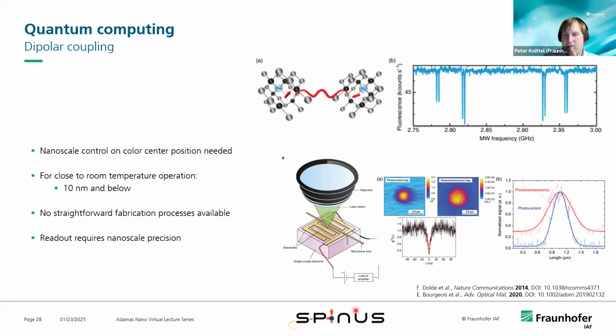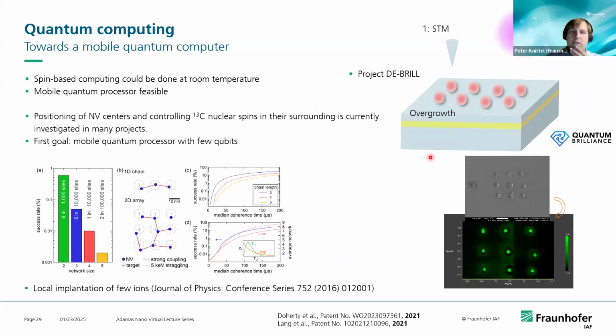We're also working on that in the European project Spinus and in a German-funded project together with Quantum Brilliance. These NV centers, in principle, may be addressed by a technique pioneered by a group in Belgium by Milos Nesladek, using an electrical readout, a photoelectric readout for the magnetic resonance signal, and with that it may be possible to even address these NV centers spaced a few tens of nanometers apart. But again, this is a very challenging approach. A bit easier may be a photonically coupled approach, but I come to that on the next slide. Here is how we want to achieve it together with Quantum Brilliance, positioning these NV centers.